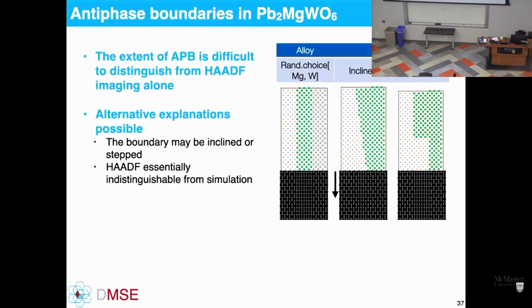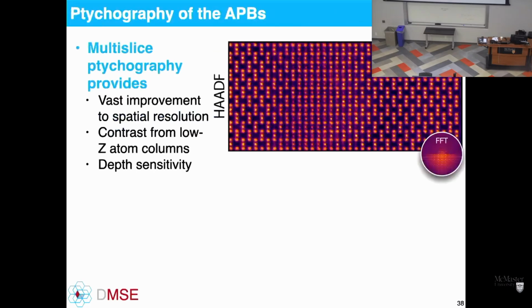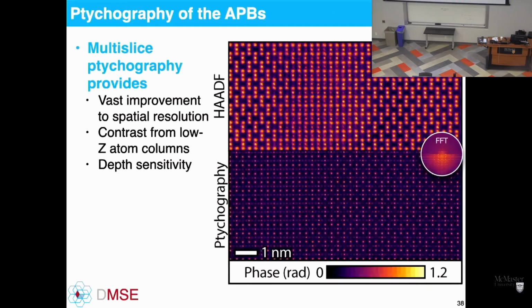From, again, STEM, you'd have to do a lot of work to try and resolve that question. With ptychography, we can acquire one data set and get the answer. So again, here's our HAADF image. Here's ptychography. Now, rather than just the heavy atoms, you also get oxygen for free, and you can get chemical sensitivity out of this with three-dimensional information.